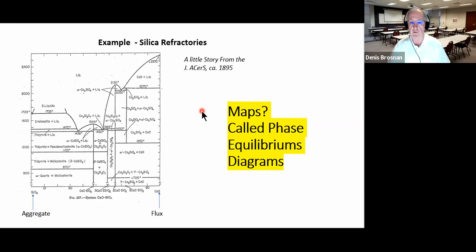But what I'm trying to get to in telling this little story, or parable, if you want to call it that, was that the British engineer knew that the flux, the lime, would create liquid within the ceramic. So we can use phase diagrams. We can use maps like this to figure out where the eutectic points are in our systems. Sometimes, of course, the systems have multiple components, not just two components like silica and lime, but we can use phase equilibrium diagrams. So that's a much more refined approach than just guessing, than doing trial and error.